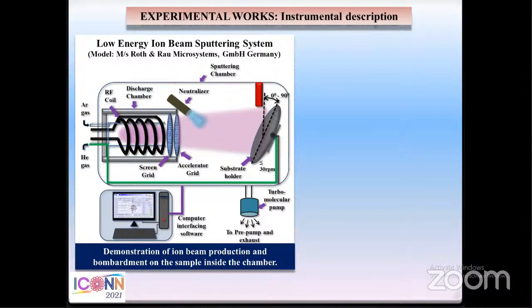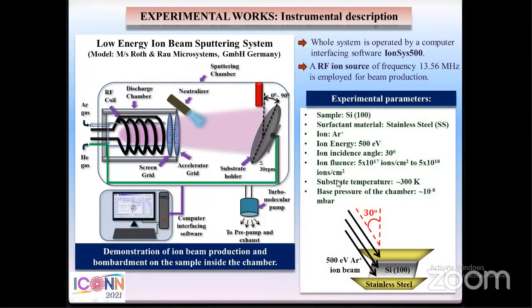So, coming to my experimental work, this is the schematic of the low energy ion beam instrument we have employed to generate such kind of nano patterns on various surfaces. So the heart of the instrument, that is the ion beam source, is an RF ion beam source, and moreover the whole system is operated by a computer interfacing software. So these are my experimental parameters. Here I have used a silicon 100 p-type substrate as my sample, and as a surfactant material or co-sputtering sample, I have used the stainless steel target. Moreover, we have used argon.